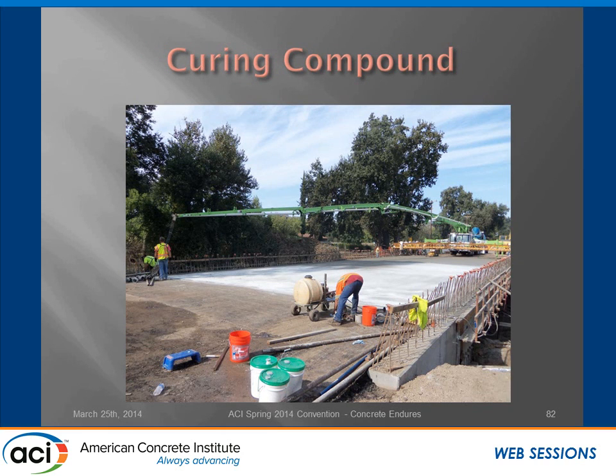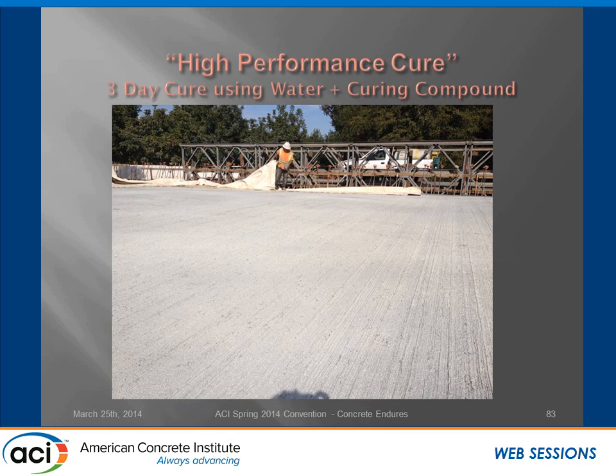We did a 3-day water cure on this bridge, again, to accelerate the bridge construction, and we decided to come up with what I call a high-performance cure regimen. In this case, we put down our pigmented curing compound, as we normally do, and what we call our standard spec cure. We came back with water and rugs for 3 days. On the third day, we pulled the rugs and, as the deck was still damp, applied another coat of curing compound and let it set up before we put traffic on it. This is a picture of our high-performance cure as it's being applied, as I just described.